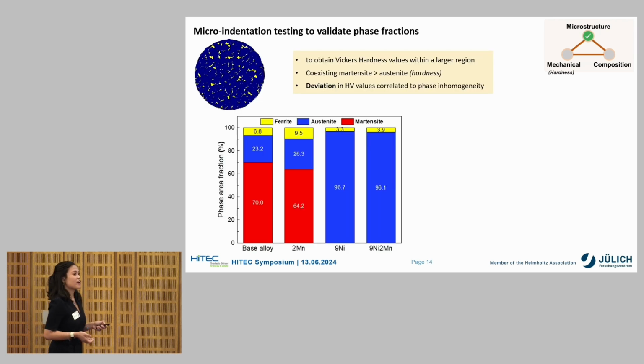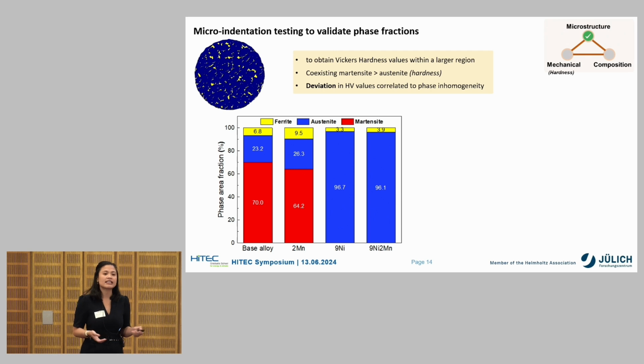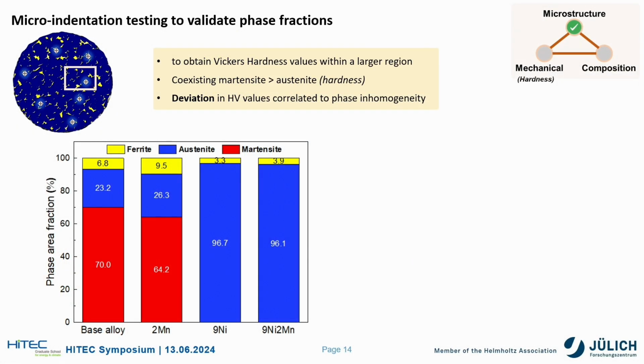Next is the phase area fractions. We want to validate the phase area fractions that were determined on a really small region within a larger polished surface. And we can do this via the technique called microindentation testing, wherein we determine the Vickers hardness values on random points within the larger region. These Vickers hardness values are correlated to the phase area fractions such that a microstructure with coexisting martensite would be harder than the one with austenite.